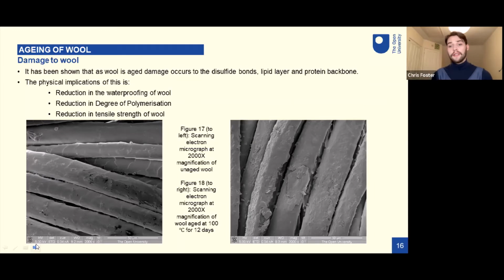On the right, you can see an aged sample. This has been aged for 12 days in an oven. You can see the effect is quite drastic. It doesn't have a defined cuticle, which is most likely due to damage to the lipid layer, but also this kind of product on the edge could be that oxidation product from the degradation reactions. You can also see areas where the cuticle is actually getting smaller and the lipid layer is peeling off. If you could go to the next.